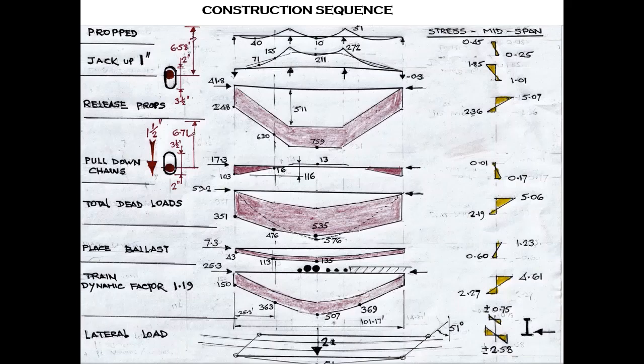What actually happened? The idea in this bridge was to induce some form of pre-stress in two ways. The first way was to construct the 98-foot span on intermediate props to support it, and then jack up to induce an upward pre-camber, if you like. When the bridge was pre-cambered, attach the chains, make sure they were fully in tension, and then release the props. That was the idea, and the idea was to jack up between 1 inch and 2 inches. That was what was laid down. I believe they only ever jacked up 1 inch. The reason is if you jack up more than 1 inch, the ends lift off at the abutments. I'm pretty sure they would never have anchored the ends down. So they jacked up 1 inch, released the props, and then you got the full dead load coming in and an effect of the pull of the chains.